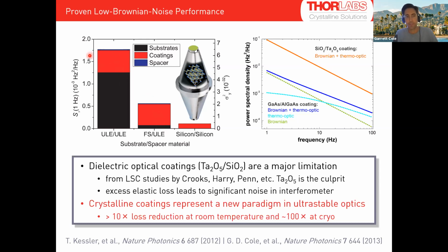So I'm looking at the plot to the left, which is the total noise as a function of material selection, I'll call it. And we've color-coded the noise contributions from the different components. So spacer being black, coatings being red, and substrates being, or substrates black, sorry, coatings red, spacer blue. So fused silica made a big advantage just given its higher mechanical Q. And then finally, there have been these cryogenic systems developed, either sapphire or silicon, where you have extremely high mechanical quality factors, and now you're solely limited by the coatings. By just the Brownian motion induced by the high elastic loss of the coatings.